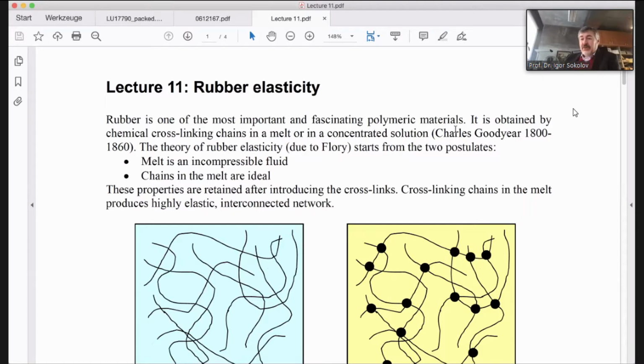If you make a ball of it, if you throw the ball on the floor, it bounces. But if you put it and let it lay for a couple of days, it flows. So it's essentially a fluid, an extremely viscous one, essentially a viscoelastic one. It's interesting what this viscoelasticity means, and I will tell you some fairy tales about viscoelasticity in the last lecture.